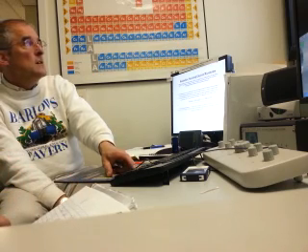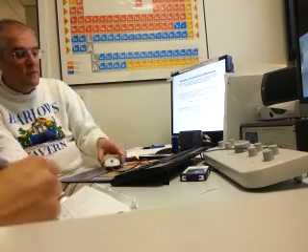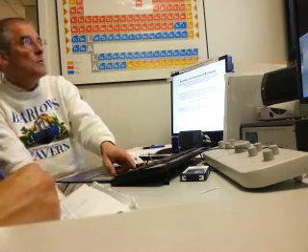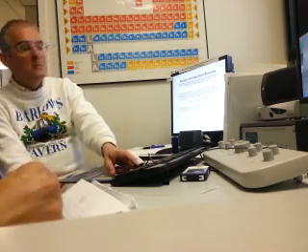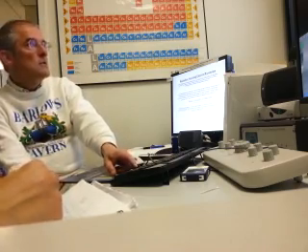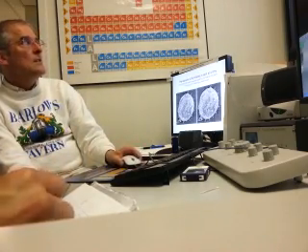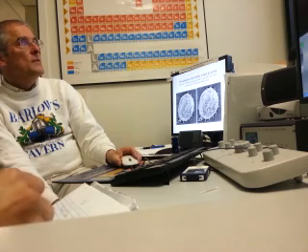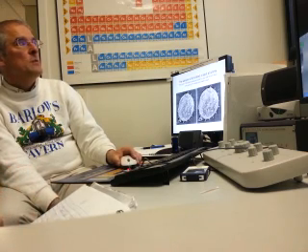Make sure you can identify what the Nyquist sampling rule is. You have to hit your sample with 2 to 3 dots in order to visualize it. More dots doesn't give you better resolution. So it's something like this. These big spots wouldn't show any difference in gray because they would all be averaged together.